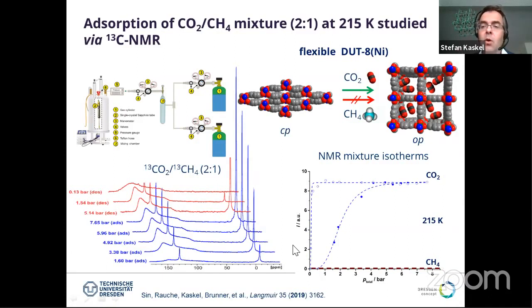And then you can also see the adsorbed molecules. In this case, we know from other experiments that the adsorbed CO2 shows a very broad signal. This is due to the anisotropy of the MOF, because it's not rotating; it's a static NMR measurement. Basically, there is a preferred orientation, or limited mobility, of the CO2 inside the pore. We can recognize this as the adsorbed state. And therefore, we observe a broad chemical shift, which is also called a tensorial property because it's associated with the tensor of this orientation.